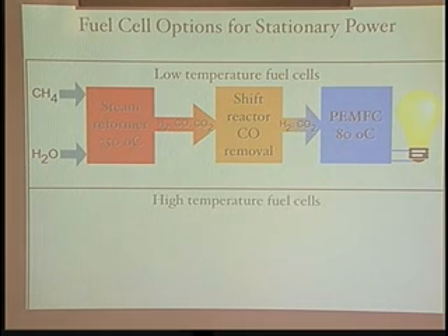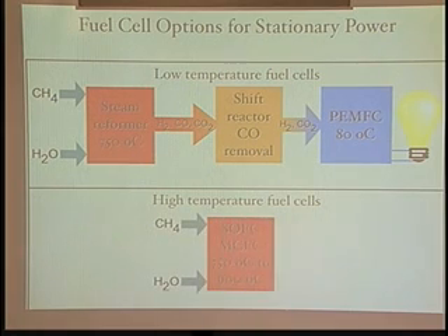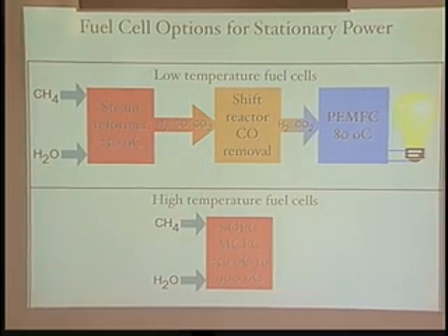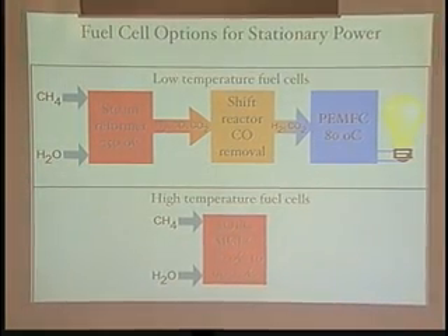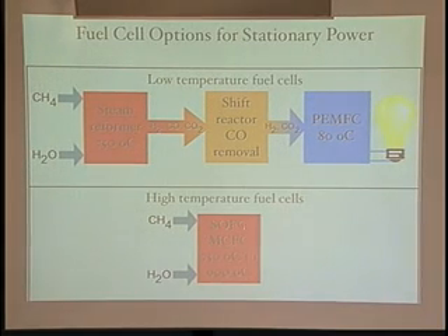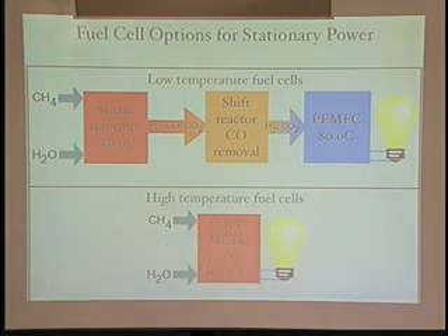So in fact, these systems don't really have an advantage over the grid in terms of efficiency. It doesn't make a lot of sense. If you look at an SOFC, a high temperature fuel cell, the water comes from the exhaust, and methane is directly fed into the SOFC, or molten carbonate fuel cell. SOFC means solid oxide fuel cell. It operates at the temperature range where reforming occurs, and these can be quite efficient. Efficiencies can be even as high as 70% if it's combined with a turbine.